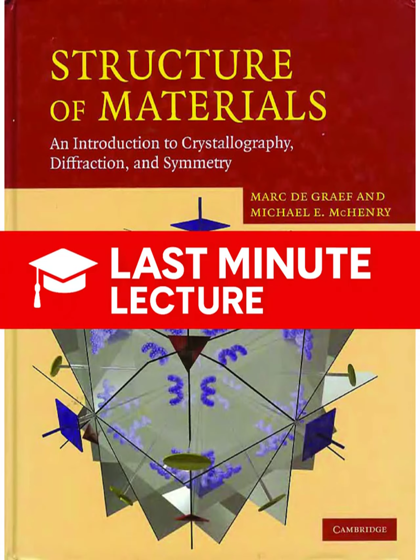And we have the phase difference, phi_j, which tells us the direction of that scattering vector relative to the origin. We combine these to define the master quantity for this entire deep dive, the structure factor, F_hkl. F_hkl is the absolute descriptor of the total scattering amplitude from the entire unit cell for one specific reflection, hkl. It is the mathematical encapsulation of both atomic identity through f and atomic position through u, v, and w.